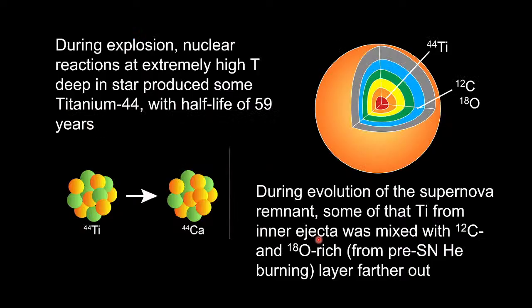So, relevant to my Stardust chronicle, during the explosion, one of the important isotopes that's made is called titanium-44. And this is happening during the explosion. When the star explodes, you're at such high temperatures and densities that you have all kinds of crazy nuclear reactions going on. And you make something called titanium-44, which has a half-life of only 59 years, and it decays to calcium-44. And when this supernova was exploding, some of that titanium from way inside got mixed out to outer layers, to say the carbon-rich layer, which also has oxygen-18, I'll mention that, from the nucleosynthesis that happened before the star exploded.